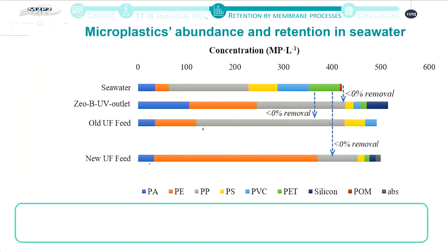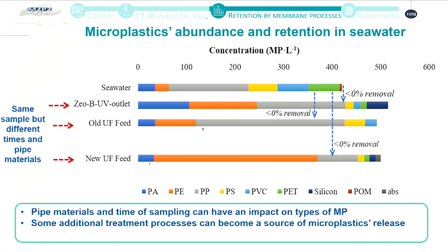If we look at the results, in the seawater you can see that we have more than 400 microplastics per liter. Here, the log scale was not needed. If you look at these 3 samples, which theoretically are the same sample taken after the zeolite filter, you can see that there is an increase of microplastic concentration, which could potentially be because of release or degradation of microplastic through the zeolite filter, or fragmentation from big particles into several smaller particles. We have almost the same amount, but if you look at the colors, we also have a different distribution of types, which could be because of the different time of sampling or different pipe materials between the 3 processes.